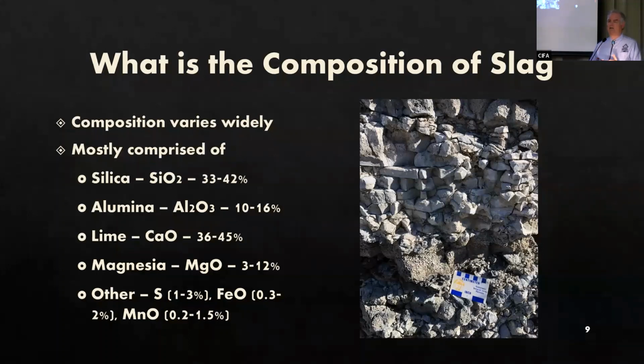Now, extensive analyses of slag from blast furnaces in the United States in the 20th century give us this range of compositions. So the silica, you can see, varies between about 33 and 42%. The alumina between 10 and 16%. The lime, 36 to 45%, almost like the silica. And then the magnesia, 3 to 12%. And then those other components such as sulfur, 1 to 3%. We were talking about breaking the slag beforehand and how you could still smell the sulfur from the slag. Iron oxide up to 2%, and manganese oxide up to about 1.5%.